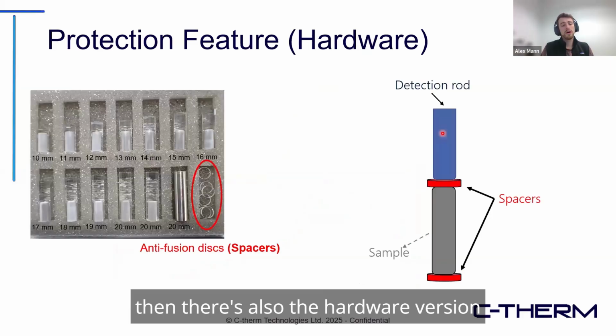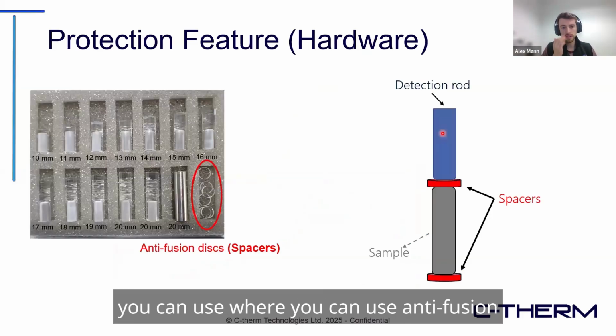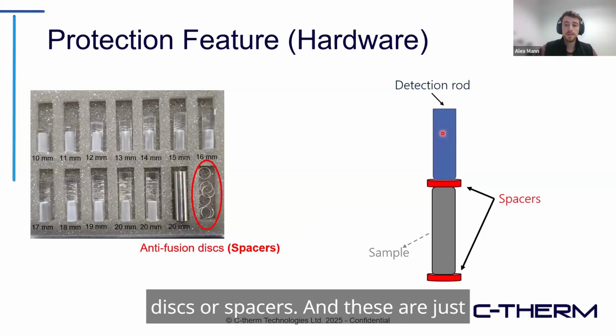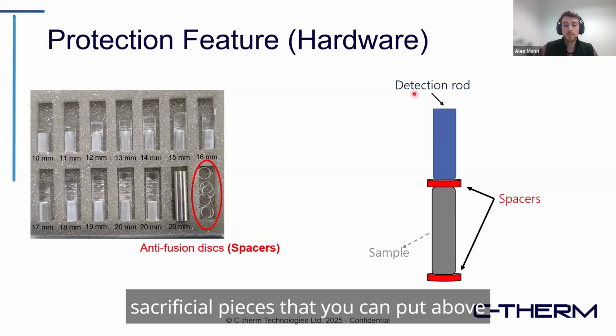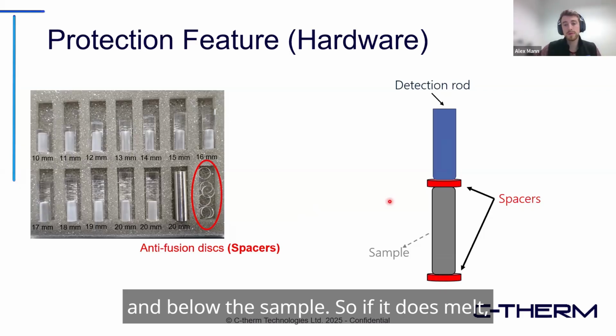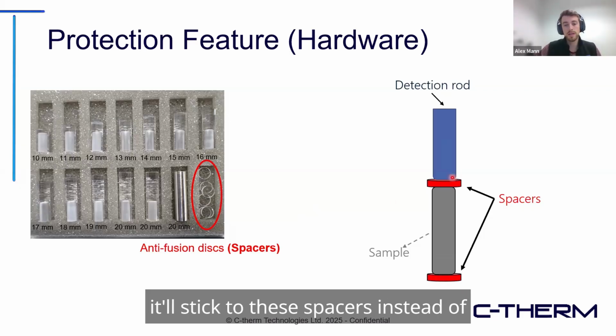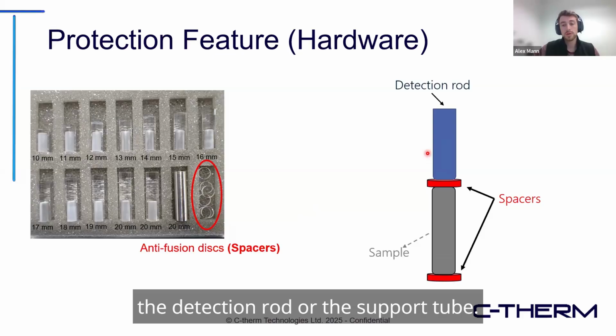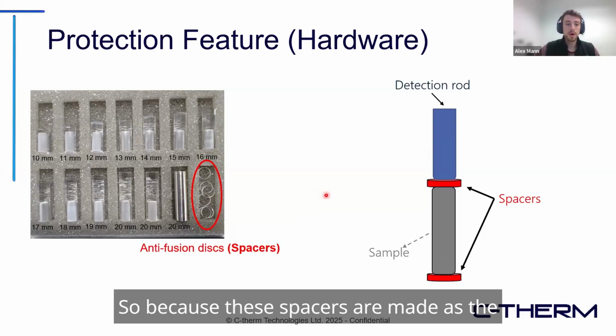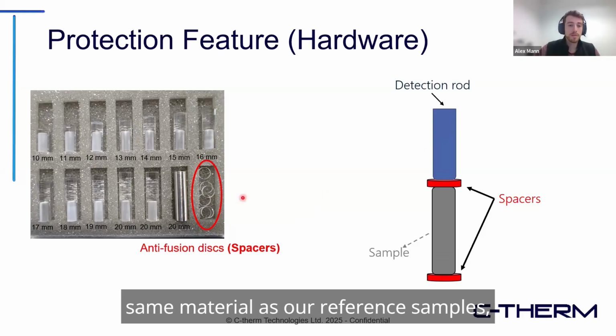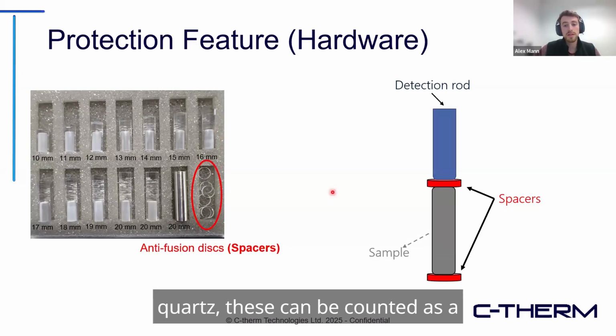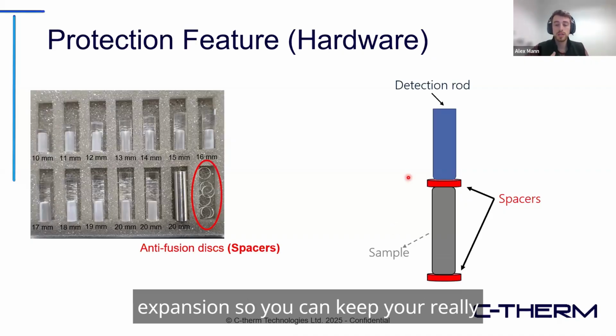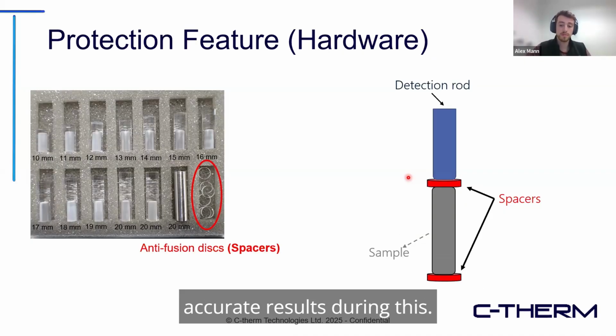And then there's also the hardware version you can use where you can use anti-fusion disks or spacers. And these are just sacrificial pieces that you can put above and below the sample. So if it does melt, it'll stick to these spacers instead of the detection rod or the support tube. Because these spacers are made of the same material as our reference samples, quartz, these can be counted as a stage, and we can factor out their expansion so you can keep your really accurate results during this.